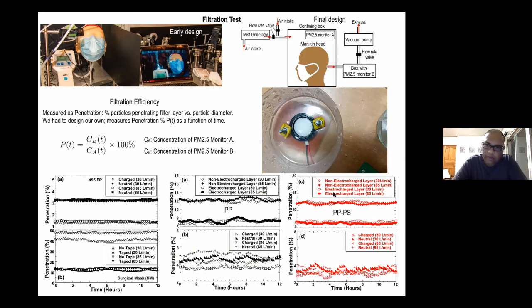That is for polypropylene. For the polypropylene polystyrene mix, I get more or less the same results as for polypropylene with the surgical mask. But when I look at the 3D printed mask results, the extra charge retention of polypropylene polystyrene actually takes it below the 5%. So this is the 5% line, and for all four tests, I got below 5%. So this material did better than polypropylene, getting me within the N95 mask requirement.